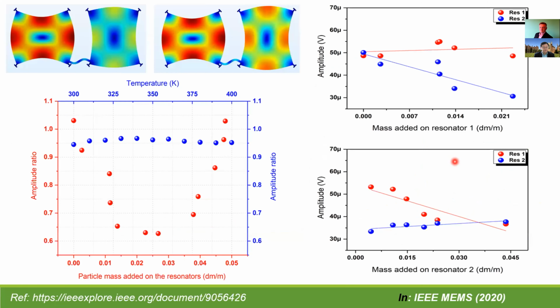So what we have observed is, when particles were deposited on the first resonator for about 5 minutes, the amplitude ratio, which was initially at 1, tends to diverge based on the mass which is deposited on the resonator. Then when we proceed to deposit mass on the second resonator, the diverged amplitude ratio converges and tends to become 1. So the amplitude ratio starts at 1 and goes back to 1.